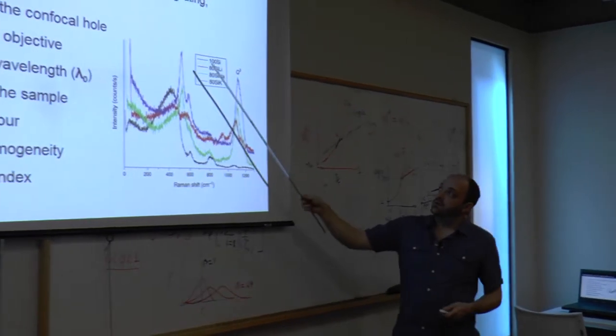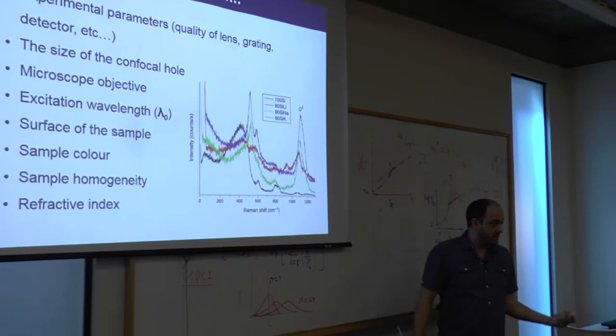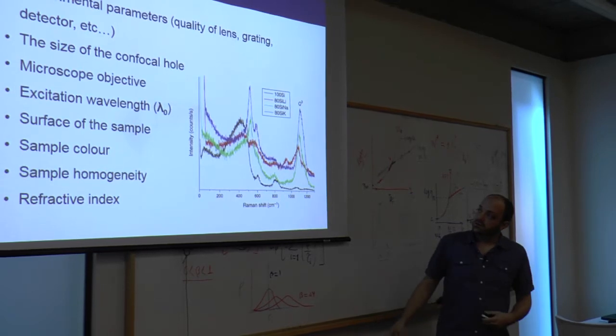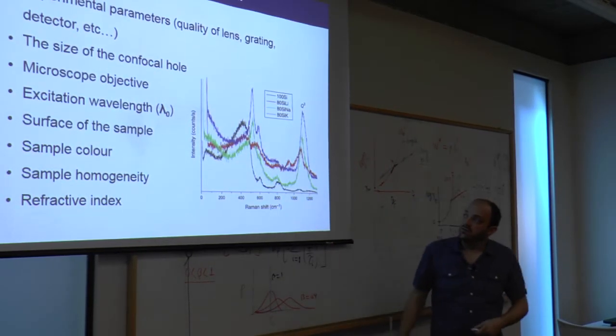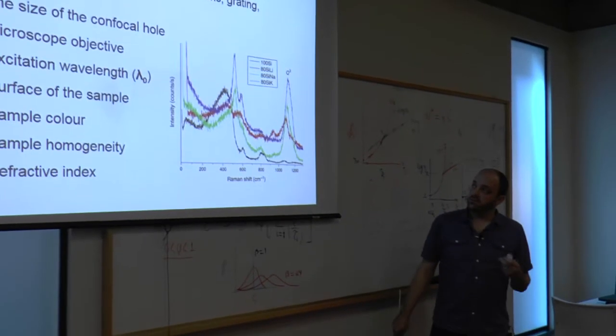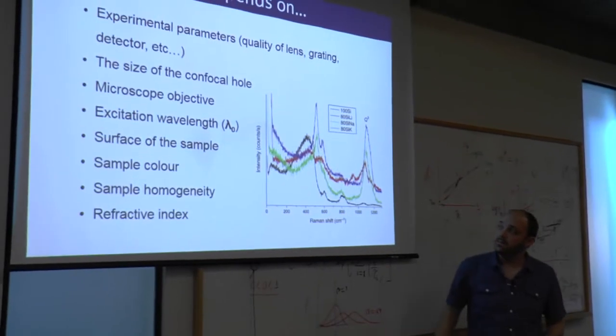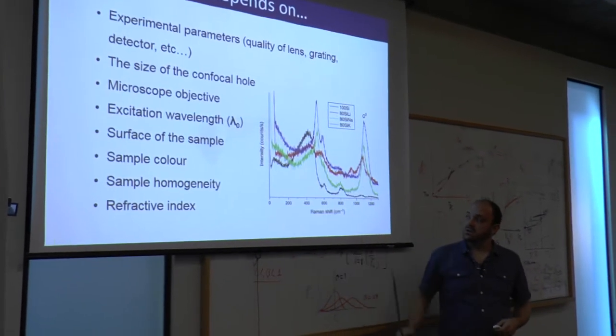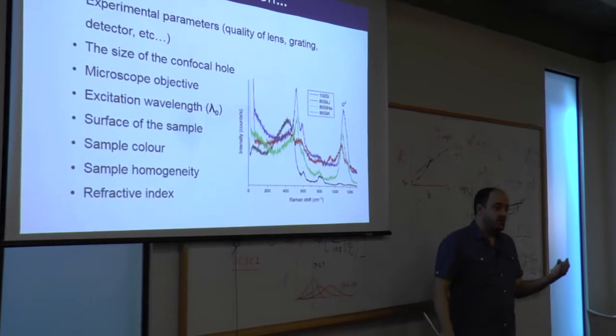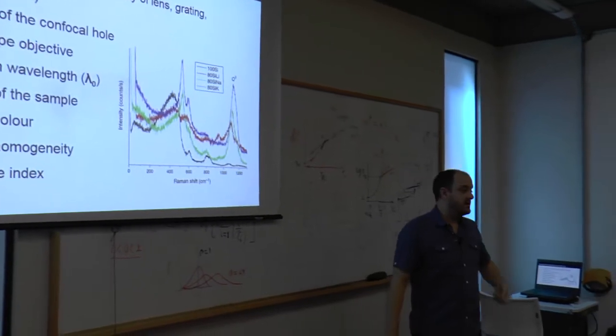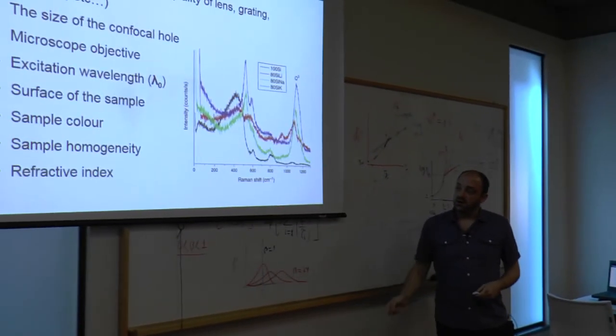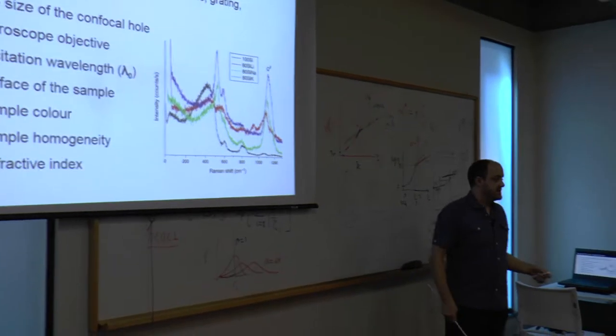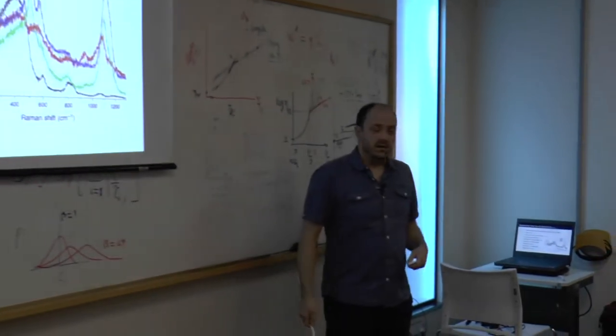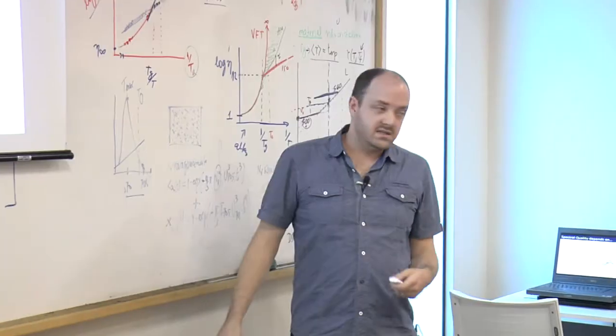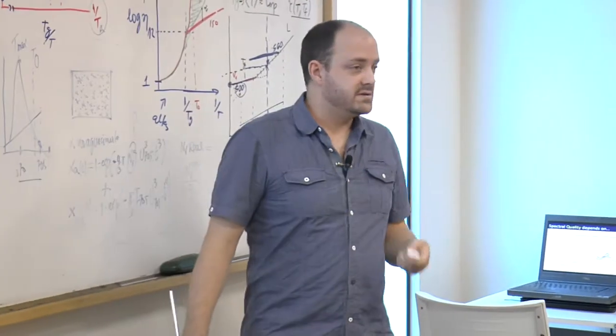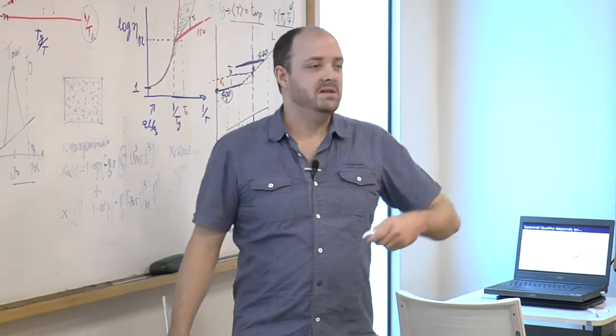So first of all, the quality of your overall detector, the quality of the lens you're using, the different gratings all go into improving the signal to noise ratio. How much light, which is controlled by the confocal hole, how much actual light is scattered off your sample and received by the detector, what objective you're using, what wavelength, and this is really important, we'll see in a second. The surface of the sample, if it's not perpendicular, you're going to get a lot more scattering off to the side and the detector's not going to see that. Sample color, homogeneity, the refractive index, all of these factors you really have to get some experience with to determine what's best for your sample. So it does take some trial and error at the beginning. Or you work with somebody who's an expert who already does it with that specific application, and then they save you a lot of time.